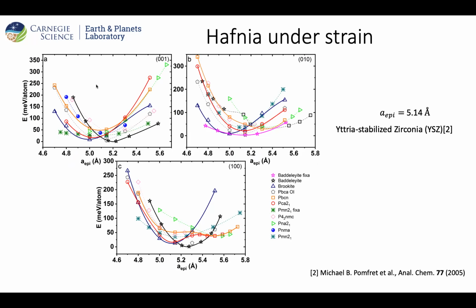First, depending on the strain, the most stable state is the Baddeleyite. This confirms experimental observation. But depending on the epitaxial strain that you apply, you can actually stabilize, for instance, the Pmn21 phase when you uniaxially strain it, or the orthorhombic PBCA.